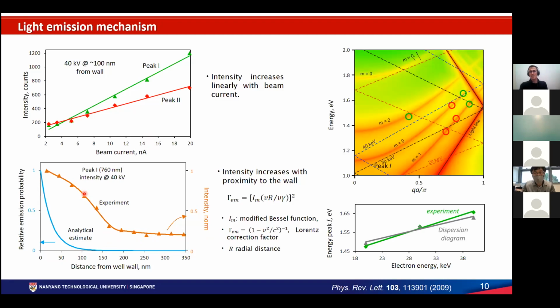And the emission mechanism itself, as I described before, is related to the Smith-Purcell, but is not purely a Smith-Purcell emission. Actually, the well is a 1D photonic cavity, so you can generate the photonic modes supported by the well. This is a very simple description, a theoretical description of the well. So it's a modulated gold well rather than a multi-layer, which becomes much more complex. But nonetheless, when you plot the light line for the speed of the electron, you see that the experimental points fall very close to the intersection between the electron energy lines and the modes of the structure.